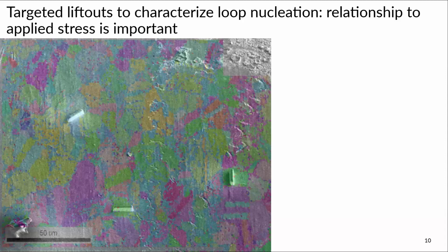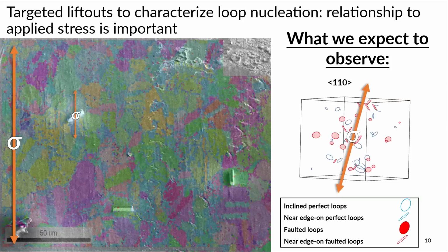So what we do is we irradiate. We then see our electron backscatter diffraction, pick a grain that is oriented in the direction we want it to. We targeted 110 just as an initial part. So I did lift outs perpendicular, parallel, and some at a degree in relation to the stress. So the stress in this case is like the y-axis. And I'm only going to talk about the lift out that was oriented 35 degrees to the axis.